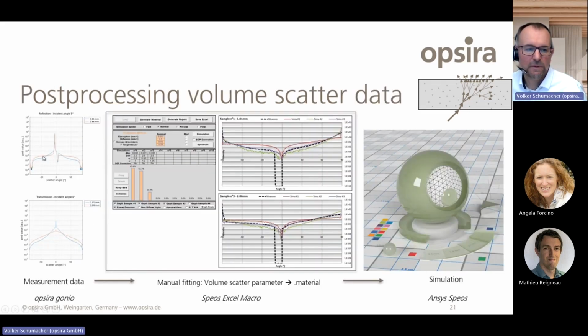When we have done this measurement, here we see again the example from before, a measurement of one type with 2 thicknesses in this example, in transmission and in reflection. Those measurement data we process in post-processing using the Speos Excel macro. This is a macro provided by Ansys, and this macro uses Speos in the background. And here we are able to introduce the volume scatter parameters of, for example, Henyey-Greenstein or Gegenbauer. Also, we can bring in absorption parameters.